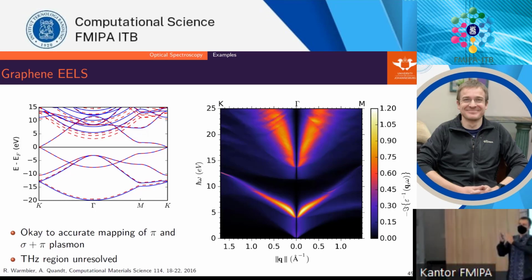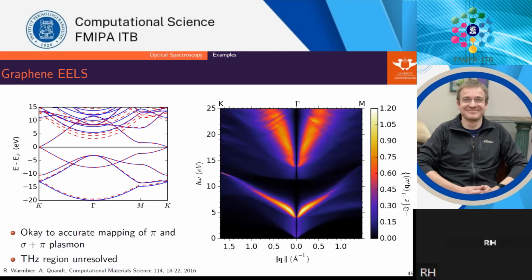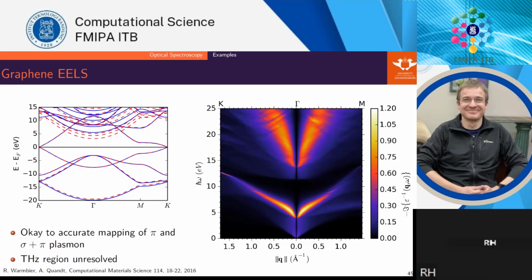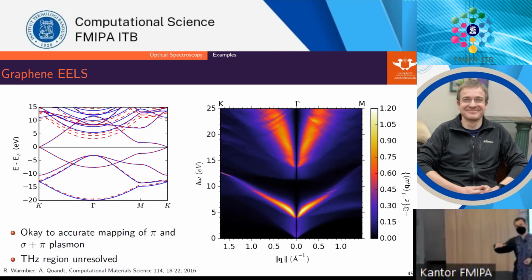So the normal plasmons you find, these big ones, can be easily reproduced using a standard equation. You start with an oscillating electric field, and then you put in electron density and so on, and you can get a plasma frequency. And if you use a three-dimensional electron gas as your starting point, you get plasmons always in the energy range of electron volts. If, however, you start with an approach where you say, I have a 2D electron gas, then the equation is slightly different. Now, it's been a few years, I cannot remember, but there was one factor that was different.